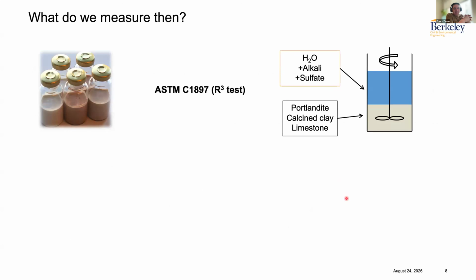From a testing perspective, this is likely one of the areas where more progress has been made in the last 10 years, and we have developed methods like ASTM C1897, the so-called R3 test, to provide a rapid and reliable way of measuring or qualifying the reactivity of a supplementary cementitious material independent of the cement that I want to use it with afterwards.